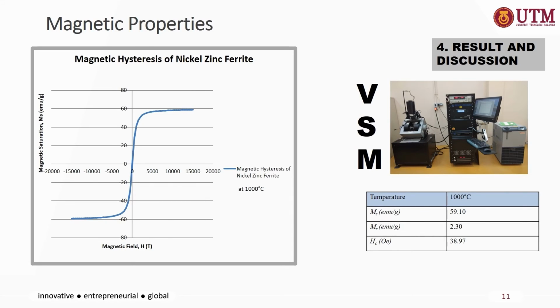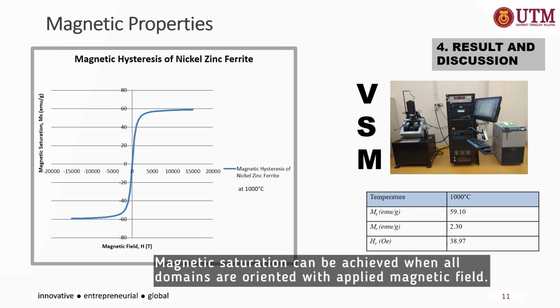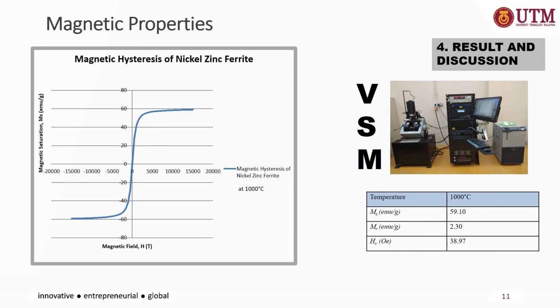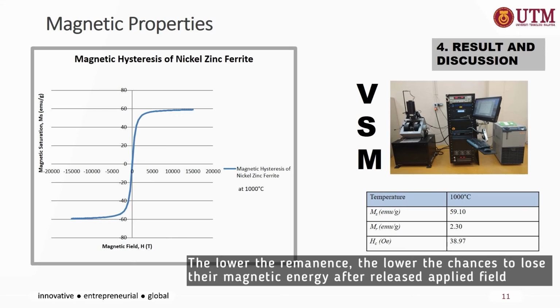We are using a vibrating sample magnetometer (VSM) for the testing of magnetic properties. The graph presents the hysteresis loop of nickel-zinc-ferrite particle at a sintering temperature of 1000 degrees Celsius. From the experiment, the value of magnetic saturation obtained is 59.1 emu/g. The remanence obtained is 2.30 emu/g, and the coercivity obtained is 38.97 oersted. The magnetic saturation can be achieved when all the domains are oriented with the applied magnetic field. The lower the remanence of the nickel-zinc-ferrite particle, the lower the chance to lose its magnetic energy after release of the applied field.